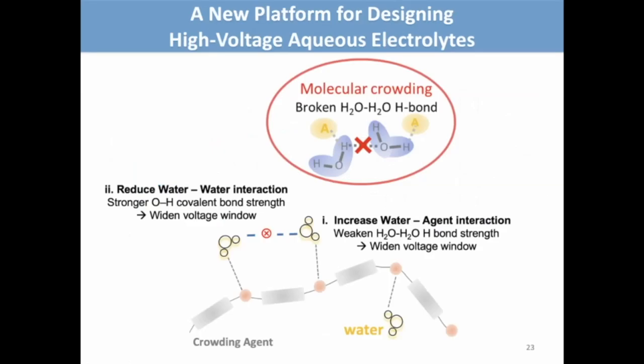So to summarize this part, we believe that this is a new platform for designing high voltage aqueous electrolytes using molecular crowding agents to break the hydrogen bond network within the water. Therefore, we can strengthen the OH stretching within the water molecule, thereby widening the voltage window and stabilizing the water.